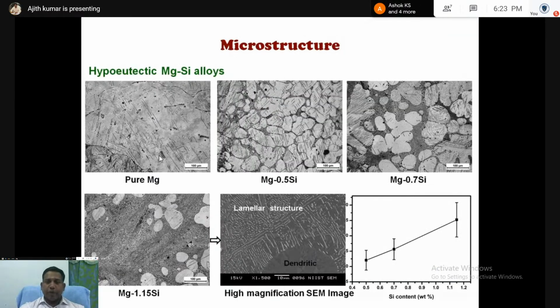These are the microstructures. This data is taken from my thesis. It is a magnesium silicon alloy. With respect to silicon content, how the microstructure is changing. This is 0.5% silicon, 0.7%, and 1.15% silicon.